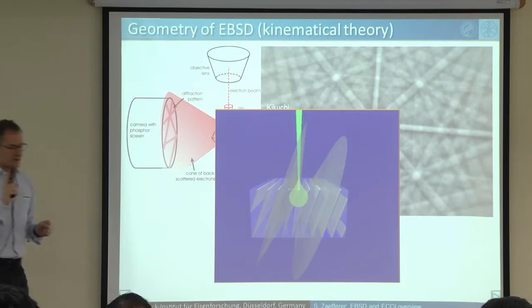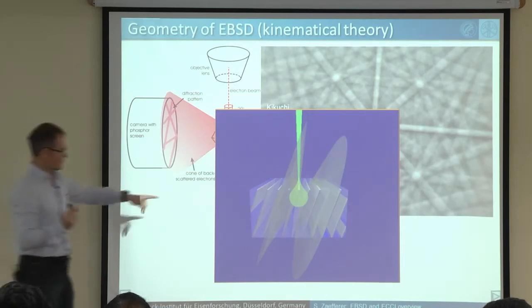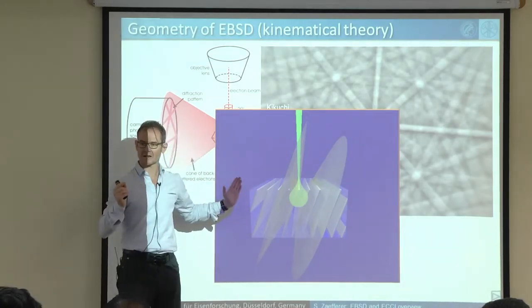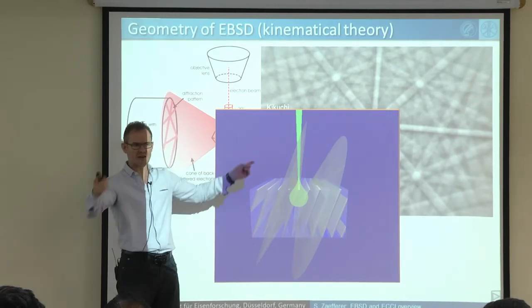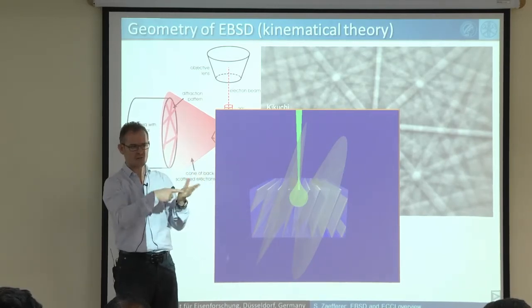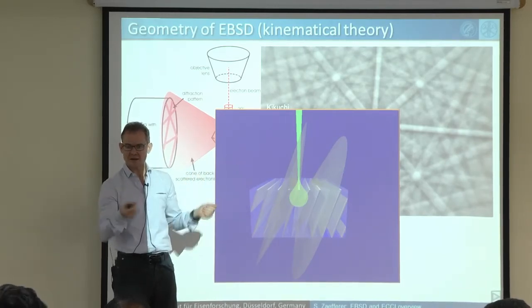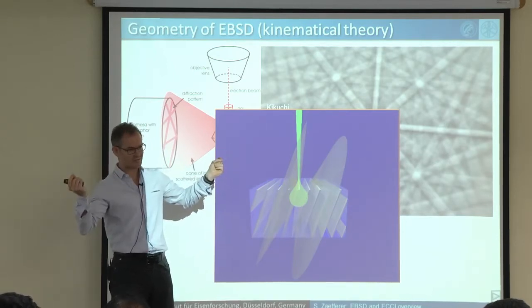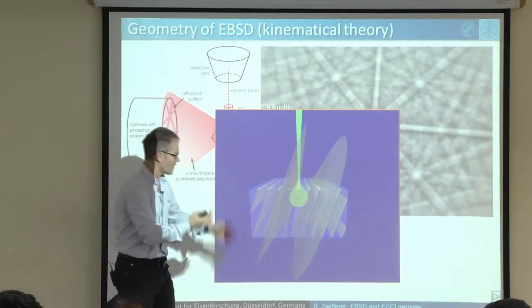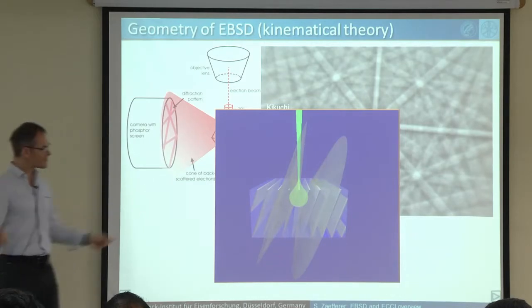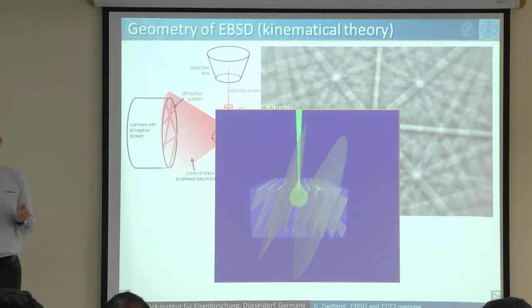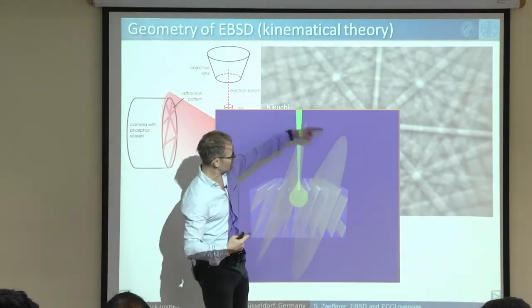And now, out of these many electrons which are traveling in all directions, you select those which, by chance, hit on these lattice planes by the Bragg angle. So you look on all these electrons, which of them are hitting the planes at the Bragg angle. And these ones will lead to diffraction, as I showed you before. Very simple. And you look, what is the geometrical locus of all these electrons? And you find, aha, it's actually these big cones here.